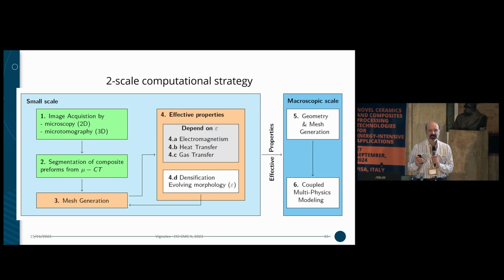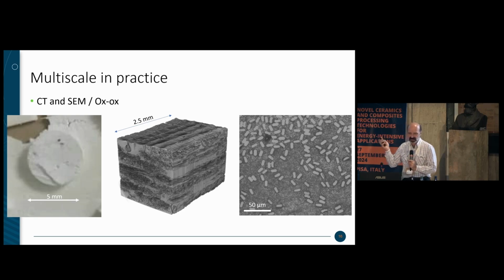So in the CEM-WAVE project, we propose a two-scale computational strategy. The first one was more focused on getting these effective properties, which depend on porosity, also on temperature, and also on the initial state of the preform. And the second block here is macro-scale computation that would be more linked to understanding how it works at the preform, at the whole part scale, okay? And this one is more on the coupled multiphysics, with, of course, the effective properties being transmitted from one to the other. So multiscale in practice is, for example, here we received, after a certain time,